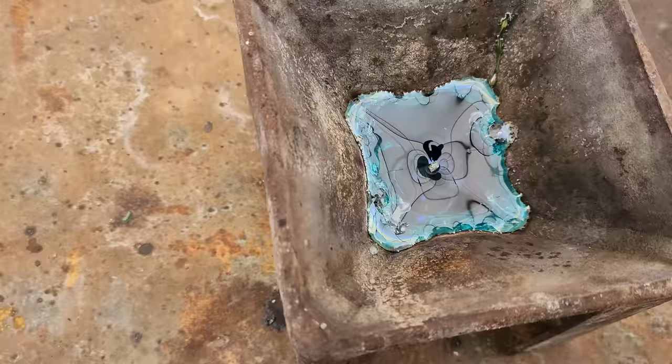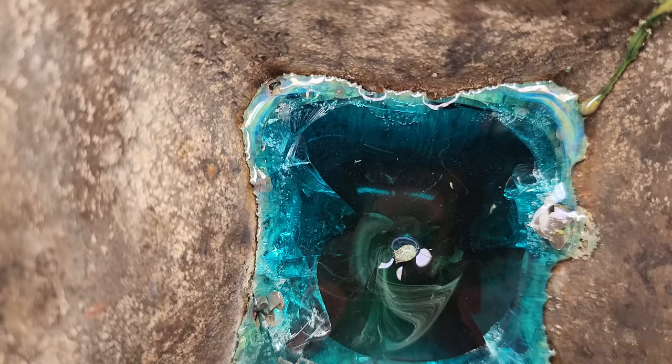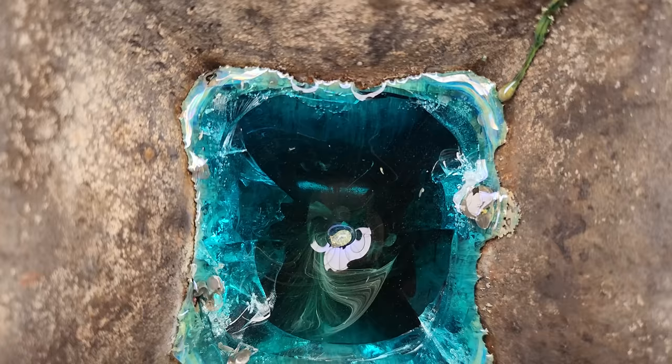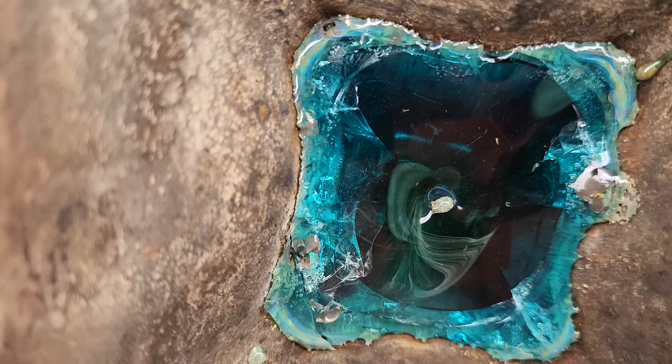We're starting to cool and crack here, but I wanted to show you, I hope you can see there, that metal edge down there. You can actually see all the way through the slag and see the silver button in the bottom. So that is unusual for me. I usually have a bunch of iron and junk in the slag. And two, it also tells me we didn't have a whole lot of base metals that oxidized. So that's good, it should be pretty pure.